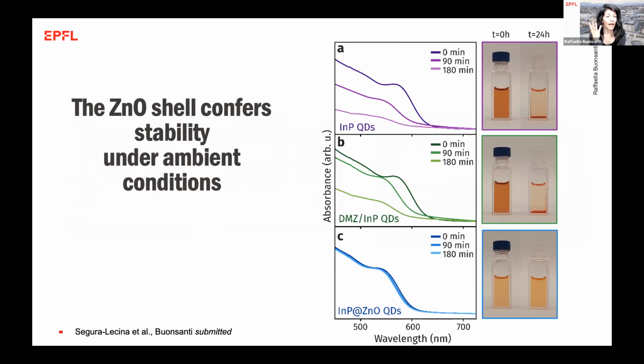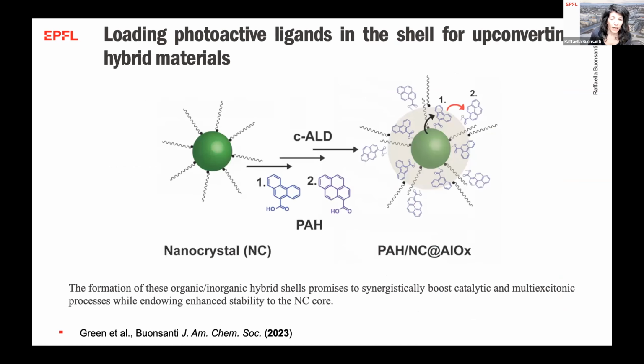And furthermore, the advantage of this shell is that we can lock the ligands in place again, and as we lock the ligands in place, we also confer colloidal stability under ambient environment to the indium phosphide, which can then remain stable for months in solution when exposed to air. Another application that we demonstrated of this shell is to create multifunctional materials, where we added functional ligands in the shell, which allow energy transfer and energy funneling from the core eventually to the outside of the shell.